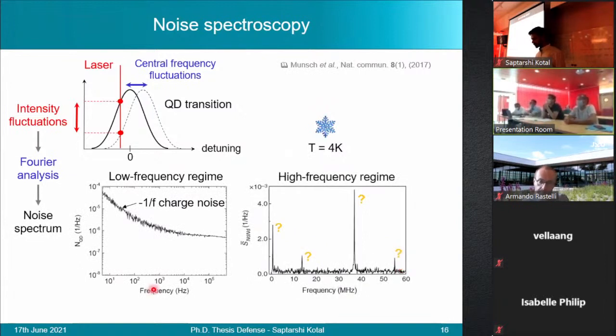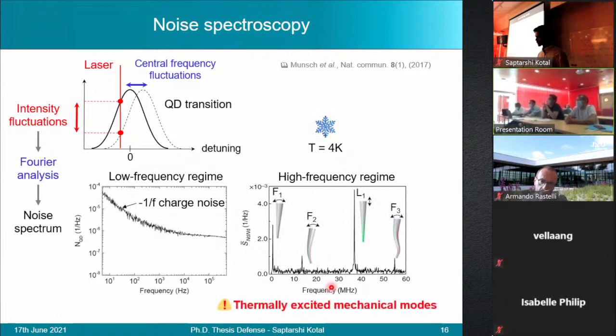Now, on the left, we look at the low frequency regime, so anywhere up to 1 kilohertz of frequency. We see that the noise spectrum decreases as 1 over f, which is often associated to the charge noise in the surrounding. More interestingly, on the higher frequency regime, discrete and isolated peaks were observed. Now, after doing some finite element simulations, this showed a correspondence to the first three vibration modes of the nanowire.